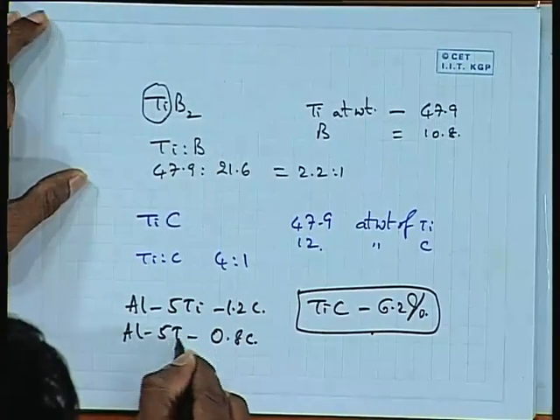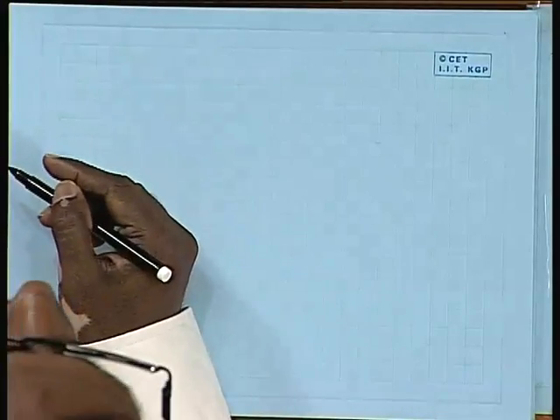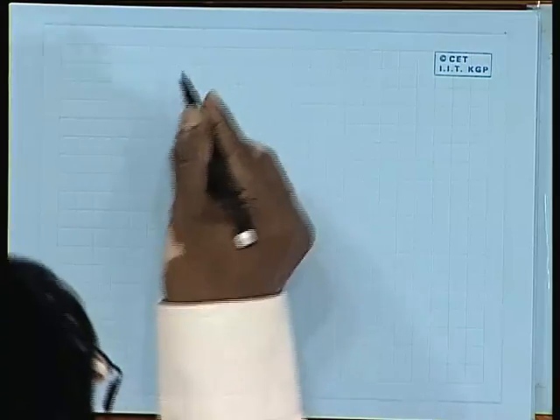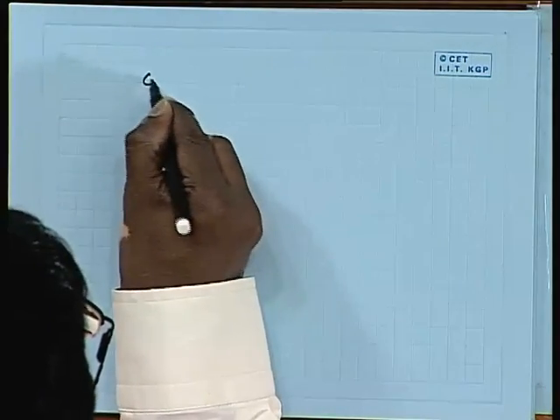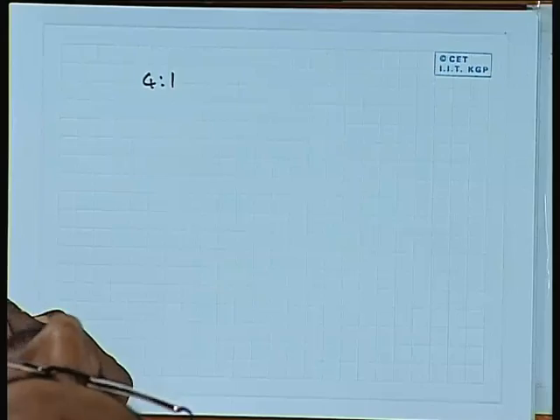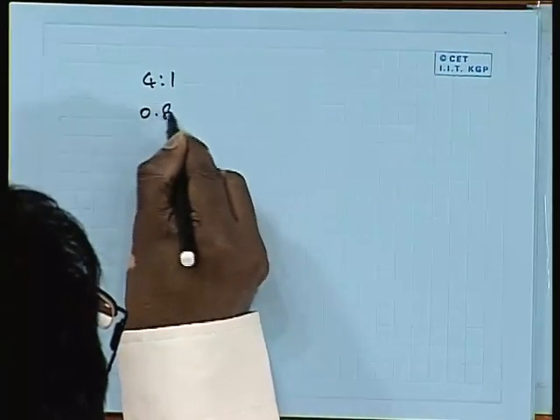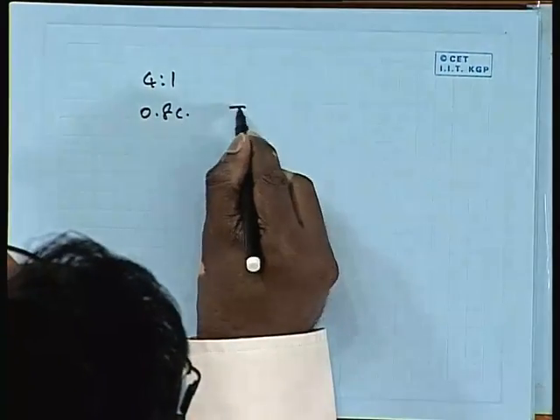So, as a result, you see that only excess carbon, for example, in this particular composition aluminum 5 titanium, one can easily calculate what is the volume fraction of TiAl3 and TiB and the TiC. For example, if you take 4:1 as the ratio of titanium and carbon, for 0.8% of carbon, how much titanium do you need?